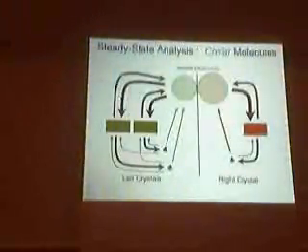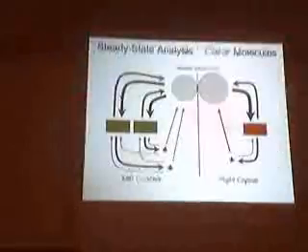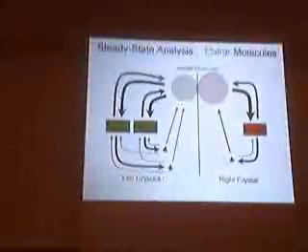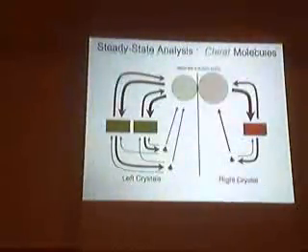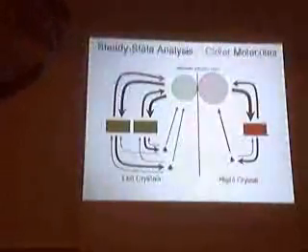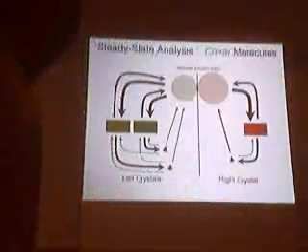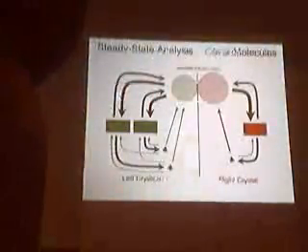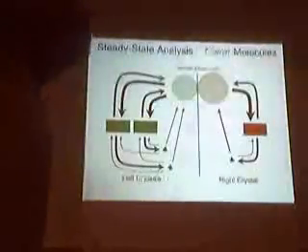Yeah. Absolutely. The only thing is that what we call Ostwald ripening is this ongoing process of dissolution of small clusters and growing of larger ones. Yeah. And I interpret this as Ostwald ripening because it's the difference between the two. You know, the reason Ostwald was interested in Ostwald ripening, he wrote a textbook this big about analytical chemistry. And the practical application of Ostwald ripening is to make crystals bigger so you can filter them more efficiently, right? Yeah. While you're grinding in a steady state, the crystals aren't getting bigger, I think.